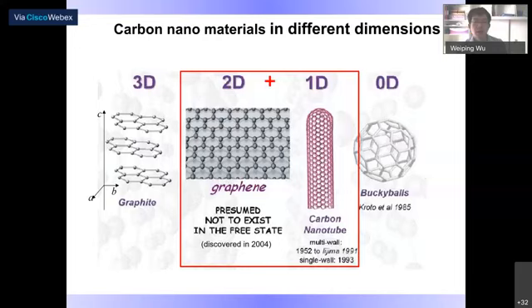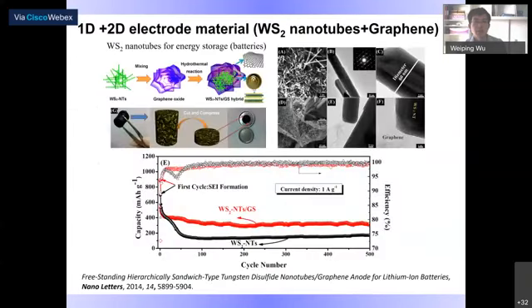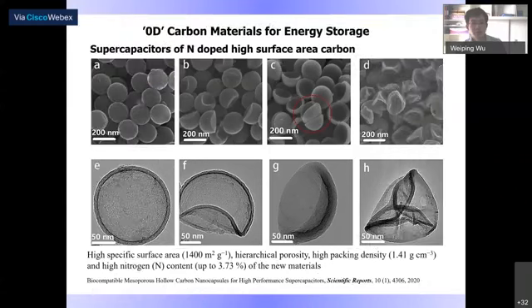I proposed a very interesting structure for the electrodes of lithium batteries. In this piece of work, I used WS2 nanotubes as a one-dimensional material, and graphene as a two-dimensional material. By compositing these two materials, the battery showed excellent performance after 500 cycles. This work has been published in the journal Nano Letters, and following that, recently I'm developing some 0-dimensional carbon materials for energy storage.